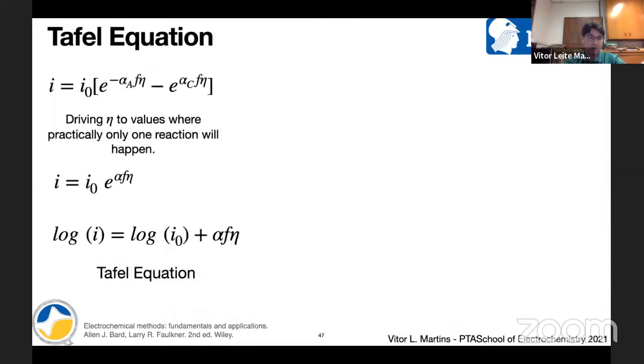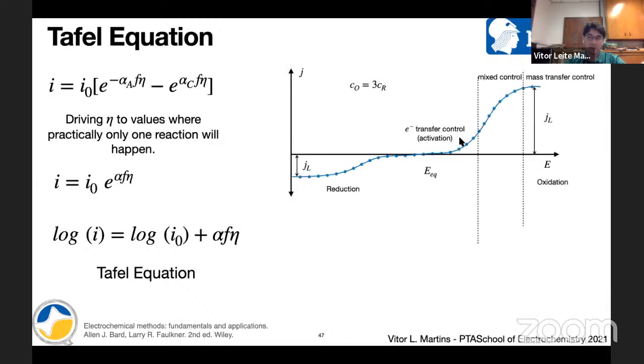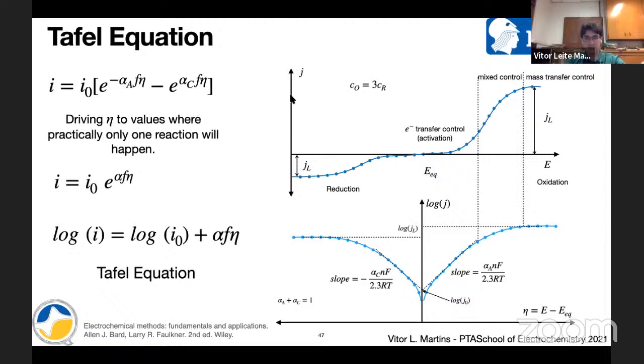So I also want to show you how the Tafel equation can resemble the other graphs that I showed you. It relates again to the Butler-Volmer, and then we can consider just one reaction happening, and you have the current depending on just these two terms. And then we can plot a log graph here. So this is showing current as a function of potential, and the bottom one is showing log of current as a function of potential, right? So if you remember from some previous slides, I showed you the activation region, the mixed control, and the mass transfer control.